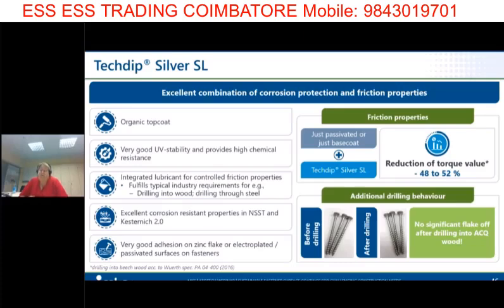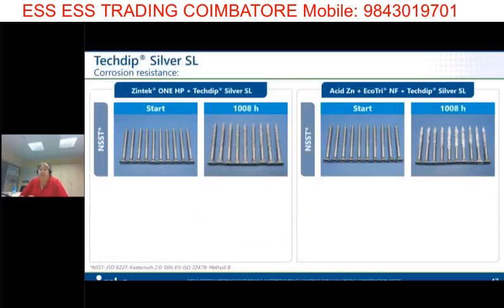Another benefit of this top coat is also the excellent corrosion resistance. Starting first with a look at the NSST, the neutral salt spray test, independent of whether we use it on top of the Zintek ONE HP, so in the zinc flake world, or if we go into our CP world by using it on top of a passivated acid zinc layer, as an example, we have no red rust after 1000 hours.